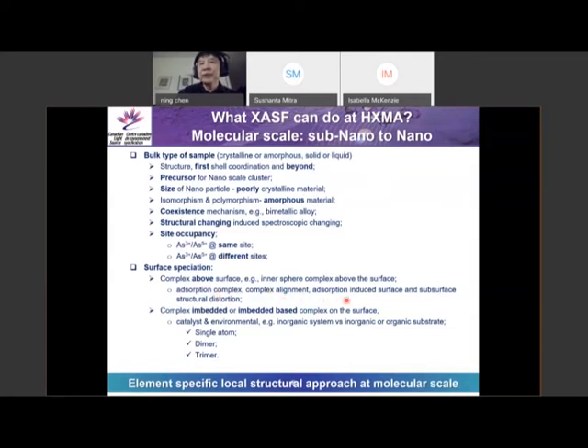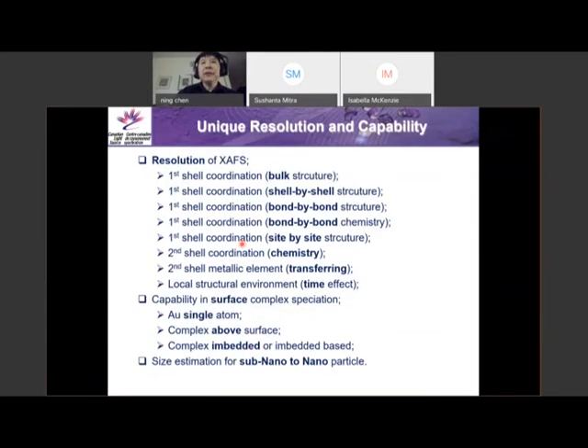We can look at adsorption-induced surface and subsurface local structure adjustment. And then we can look at complexes embedded on the surface, for example, catalyst and environmental types of issues: single atom, dimer, and trimer. So XAS is capable in the following sense: shell by shell structure for the first shell, bond by bond chemistry and structure of the first shell, and then site by site of the first shell, and the chemistry for the second shell. And also we can look at metallic element transferring within a well-defined framework. And then we can look at the time effect. So that's overall the resolution.